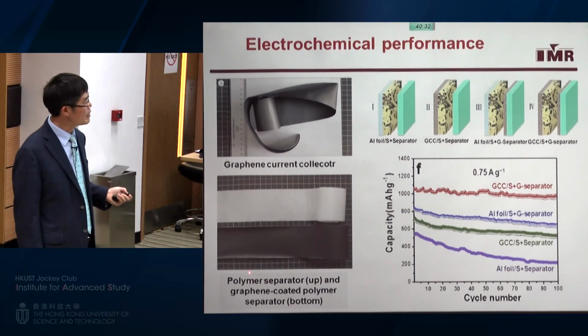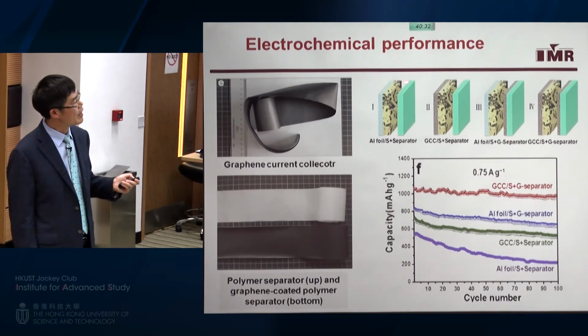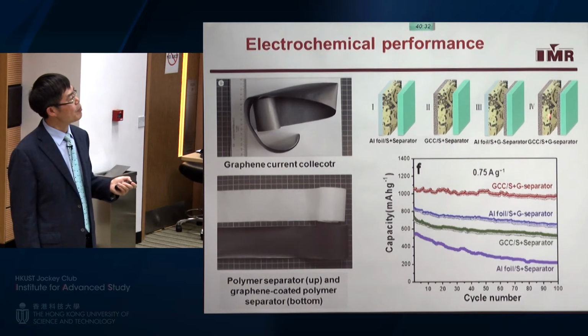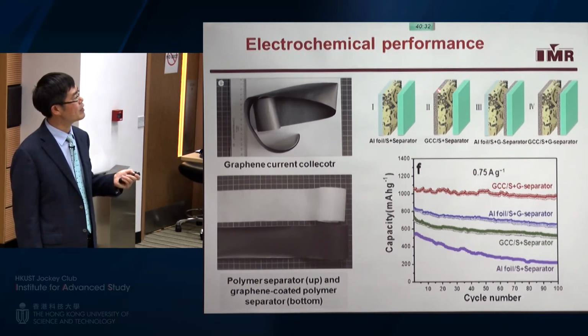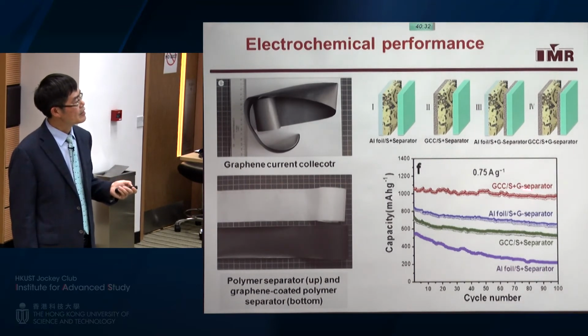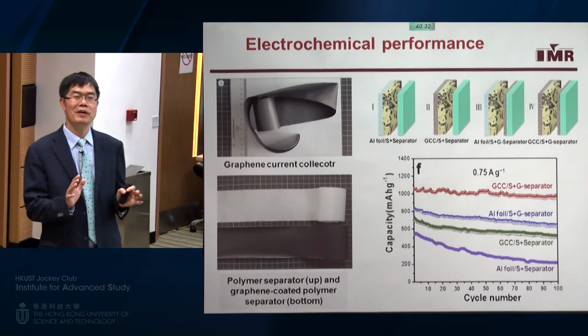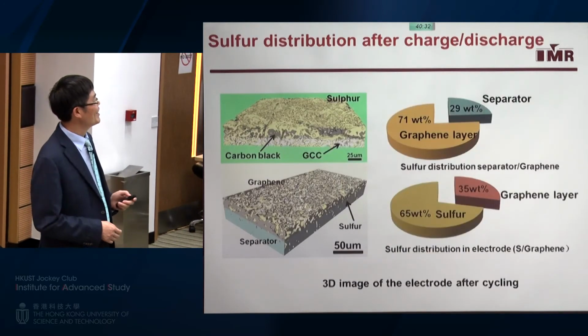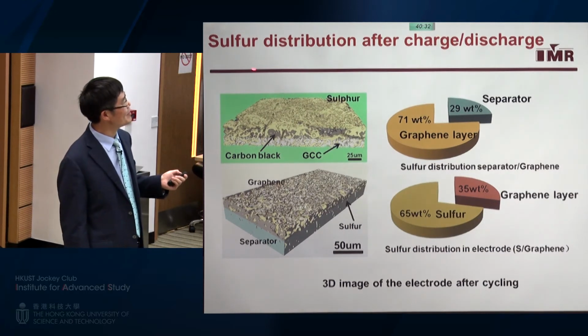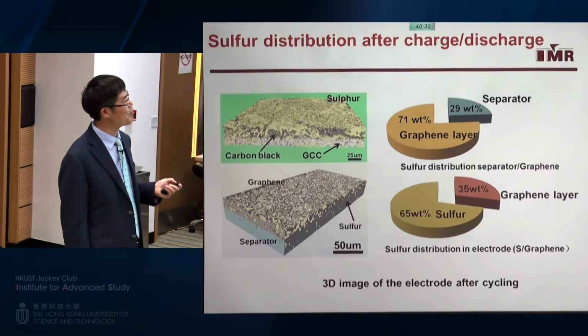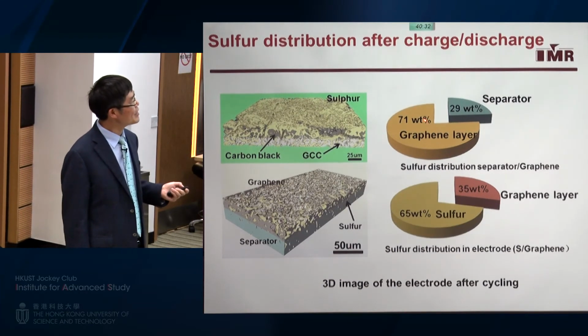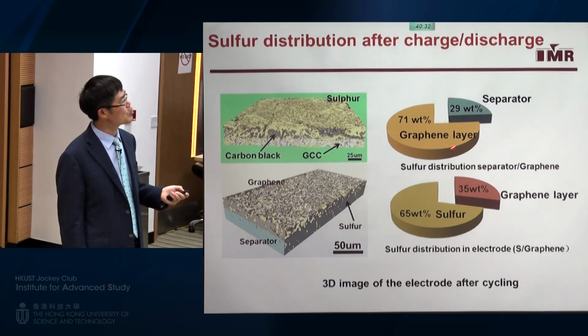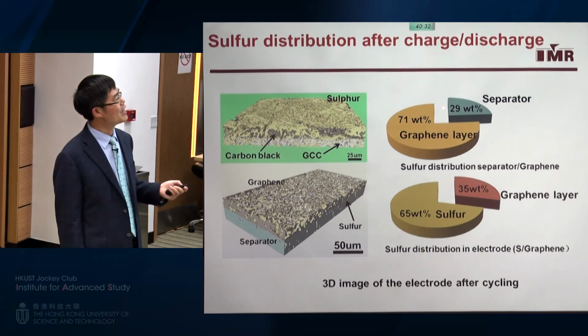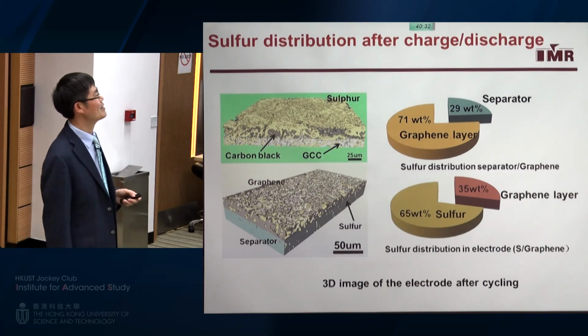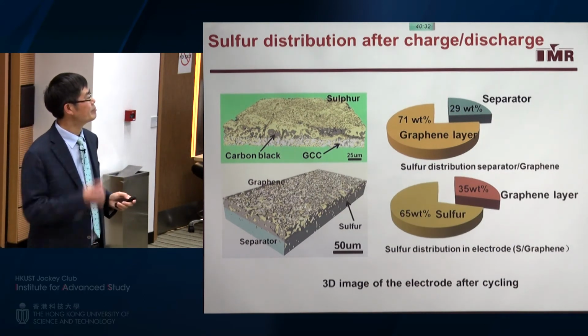So here I show you the results. This is the graphene membrane current collector. This is a buffer layer coating. We have these 4 configurations. This one is with both layers of graphene, one with one layer of graphene, another with one layer of graphene, and one without graphene. You can see this two-layer graphene configuration has much, much better performance. So that's very simple, and maybe can be used practically. We also tried to analyze the sulfur distribution by three-dimensional X-ray tomography. You can see here, about 70% of sulfur is trapped in the graphene layer, and only 29% passed through the separator.